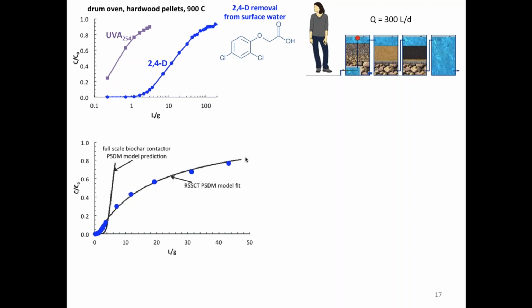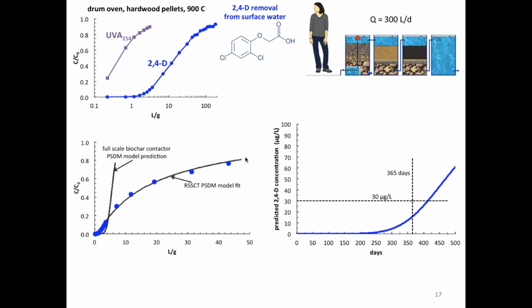And these units here on this graph are not particularly useful for considering something in the field. So if we just take that predictive curve and we put it onto more useful units like days of operation at a throughput of 300 liters per day, and we consider a high but potentially environmentally relevant concentration of 2,4-D herbicide in surface water of 100 micrograms per liter, what this graph is showing is what the breakthrough curve of 2,4-D at an influent concentration of 100 micrograms per liter might look like in a full-scale system.